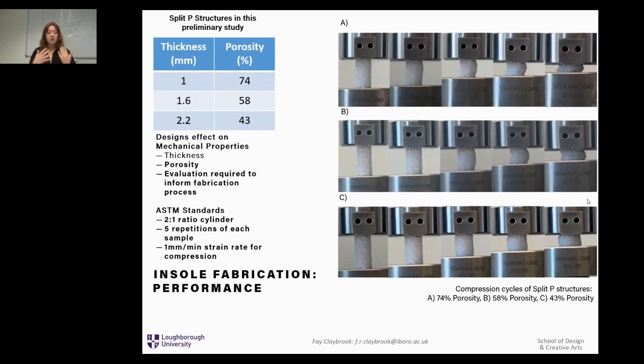So for this study, each sample was compressed under the uniaxial loading machine to see the stress strain the structure could withstand, and therefore the pressure ranges of the structure before permanent deformation. So the ASTM D695 standards were followed, where each porosity had 5 repetitions to find the averages and the anomalies. And similarly, the height was kept at 30 millimeter and 15 millimeter diameter for a 2-to-1 ratio and compressed at a strain rate of 1 millimeter per minute due to the required examining of these structures.